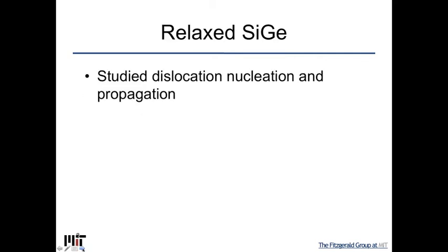So we realized that silicon germanium was the pathway to do this, and we studied dislocation nucleation and propagation in those materials because that was the key problem, as you could see from the last slide.